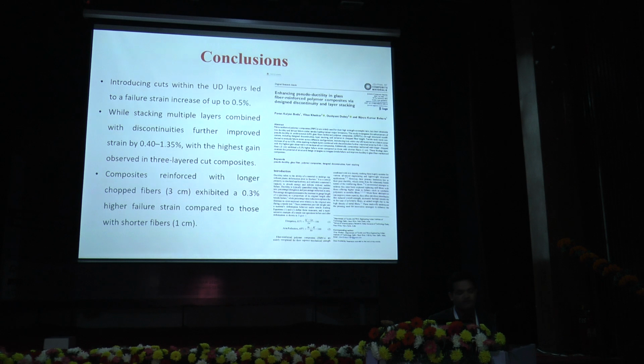And the composite reinforced with the longer fiber, which is 3 centimeters. In case of chopped fiber reinforcement, we achieved a ductility enhancement of about 0.3%.